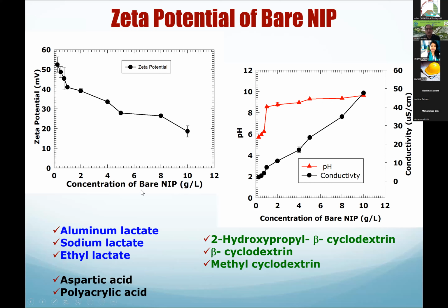So just showing that the solution, nano iron particles, you get a stock as high concentrated, and then you're diluting it. You will be using some range. You may be getting 20%, 30% as a stock solution, but then you need to dilute. The lower the concentration, better it is in terms of the economics, right? So what is the optimal concentration of nano iron particle solution that we need? But look at that. The concentration itself will have impact on the zeta potential, pH, and conductivity, and that will change a lot of different things during the reactions.